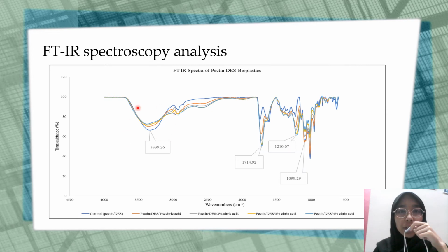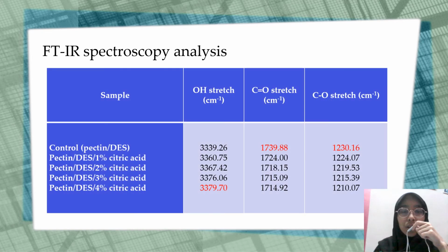The OH vibrations in this range become less intense with increasing citric acid concentration, while the C double bond O and CO bonds become more intense. These are the major peaks for the interaction between pectin, DES, and citric acid. Highest wave number recorded for OH stretch was for 4% modified pectin DES, while for carbonyl and CO stretch, the highest wave number were from control sample.